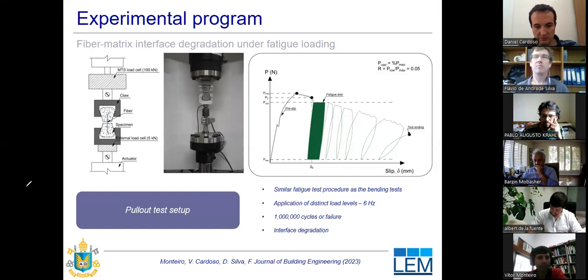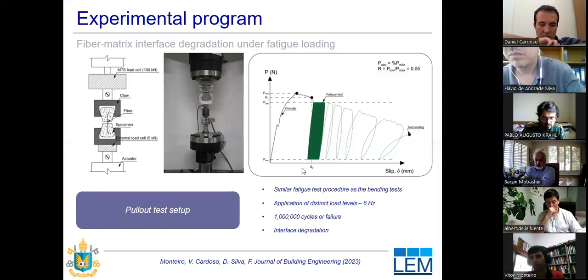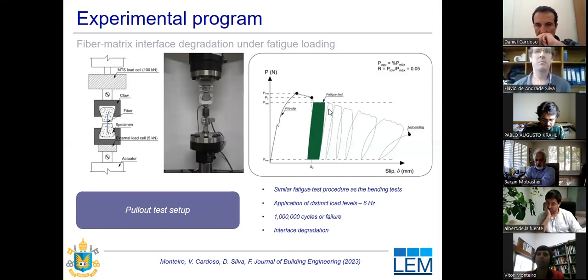The fatigue test has a methodology similar to what we have already seen at the material level. We first did a pull-out test until reaching around the maximum bond strength, and then the specimen was unloaded, and then the fatigue test began, oscillating between the upper and lower loads until reaching either a million cycles or failure in the interface. All the tests were carried out at 6 Hz oscillation frequency.